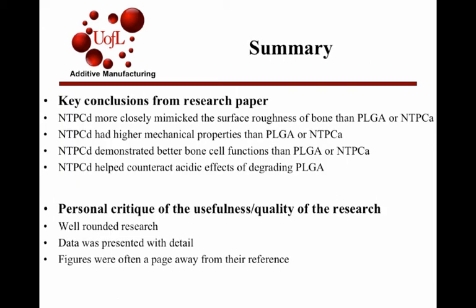Some of the other key conclusions from the research paper. The dispersed composite was more closely mimicking the surface roughness of bone than the PLGA, the NTPC-A, which is the agglomerated, or just the standard titania. It also had higher mechanical properties than PLGA and the agglomerated composite. It also demonstrated better bone cell functions than either of them. One of the other studies showed how the osteoblasts adhere to it and grow, and it actually performed quite well. It also helped to counteract acidic effects of degrading PLGA. Because PLGA is biocompatible, it also degrades in the body, which is sometimes desired. However, one side effect is it can reduce the pH in that zone, and the titania nanoparticles help to combat that, so it wasn't as harmful.